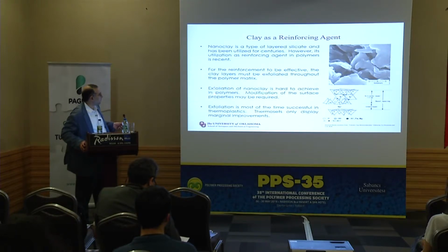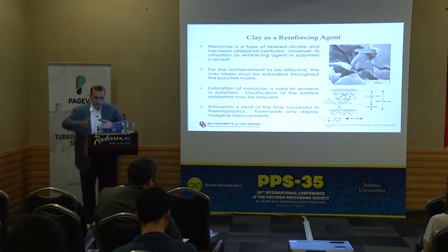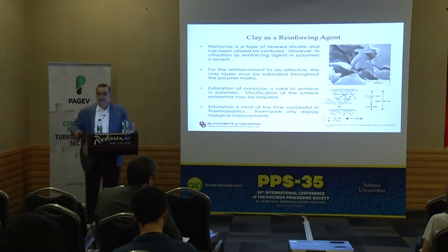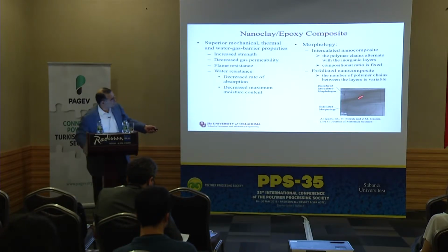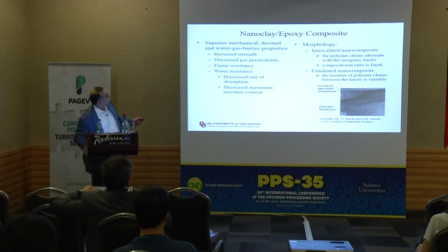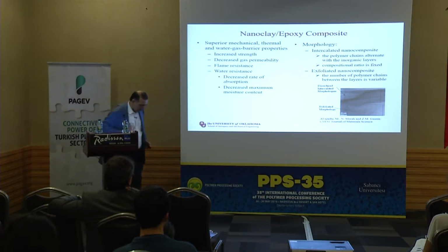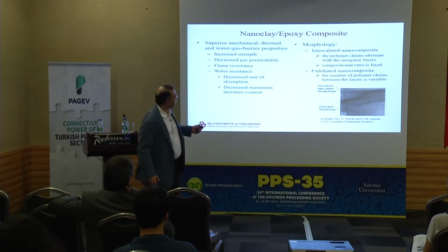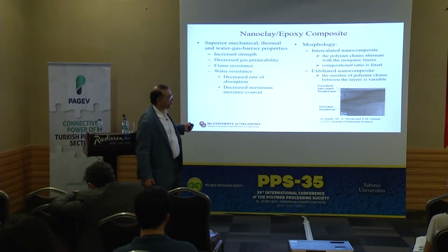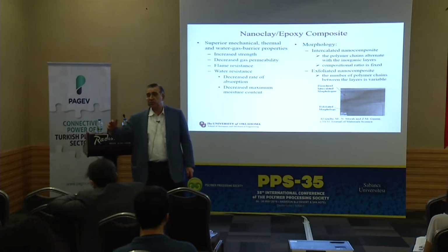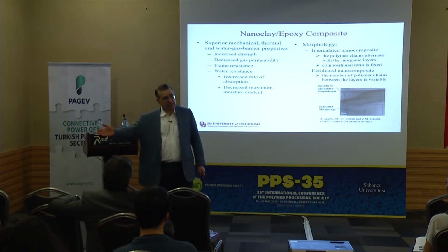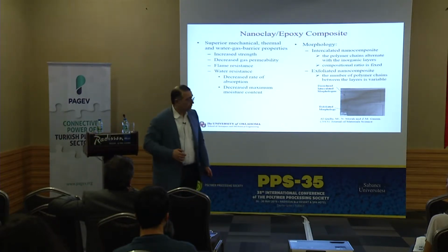Exfoliation is difficult to achieve, but once you exfoliate, it means that you separated these clay sheets or platelets on their own, and you get improvement. Maybe this is not clear, I will later show you some other ones. But you would like to increase the strength, decrease permeability, definitely improve flame resistance, and improve water resistance. But if you are not sure about the processing, you can end up reducing the strength. There are lots of studies that show that the strength of the polymer with the addition of clay went down. So it is very important how you process the clay.